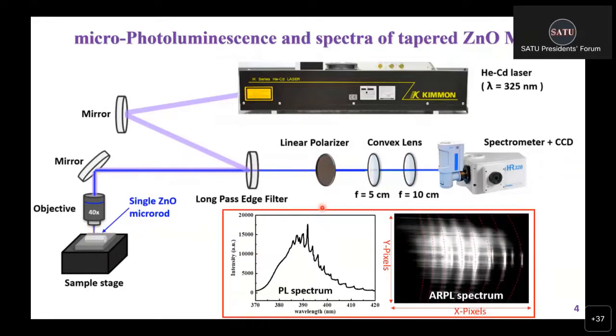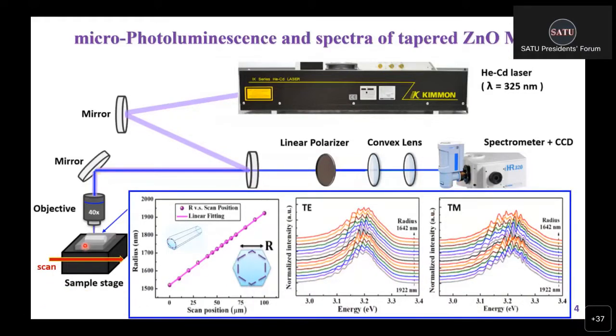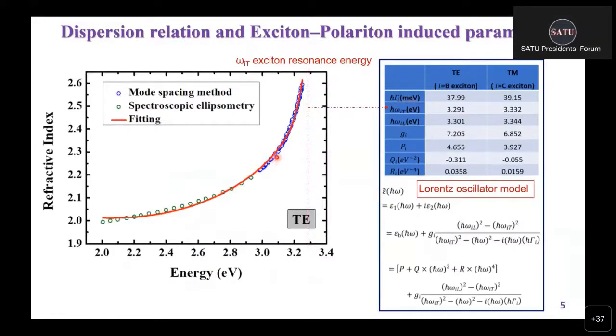And this is the multimode spectrum. In addition, the images on the CCD device, the CCD is here, the white images actually give us another important piece of information, that is the energy dispersion of the material. In particular, we choose a tapered ZnO structure to do the experiment. Because of the taper structure, different positions correspond to different sizes of the cross-section. So if we scan along this long axis, the observed modes will shift for both polarizations. By using the information of this mode shift, we can calculate the index dispersion, as the blue circles shown here.